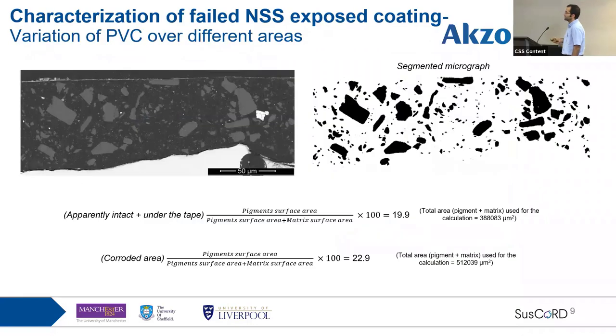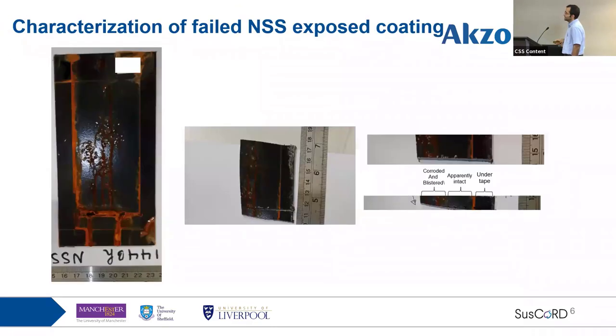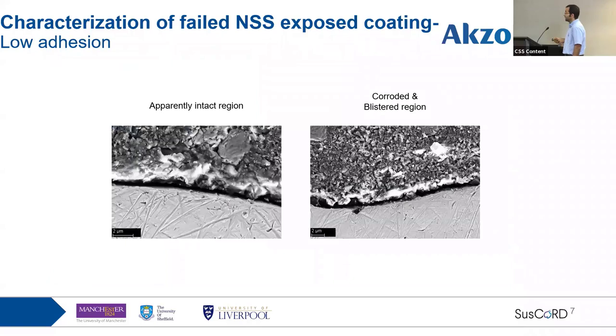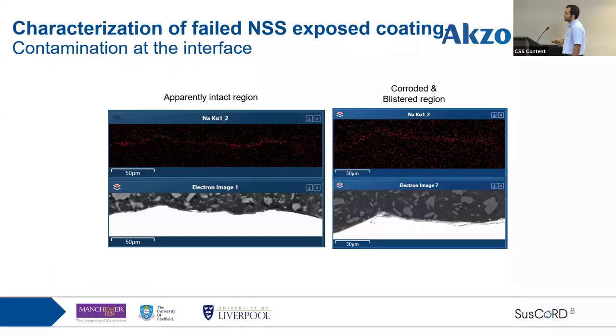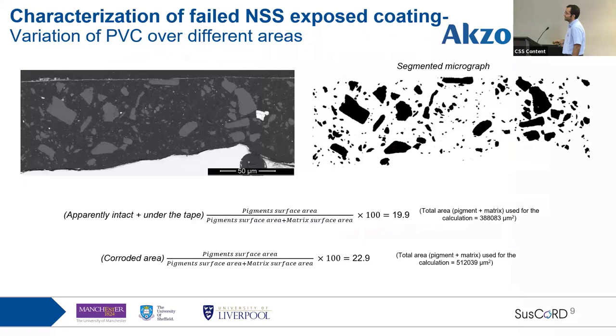And I also did similar jobs using image analysis to segment the pigments, again for the area which was under the tape and the area which showed failure. In the area which showed failure, there was a difference in pigment volume concentration. So local pigment volume concentration over the length is different, and there are higher pigment concentrations here, for a reason which I'm not clear about exactly. The coatings are applied by electrostatic guns, so I'm not sure exactly why this kind of change in pigment variation and local position may happen. But I need to talk with the Akzo people to get a better understanding of what has happened there.